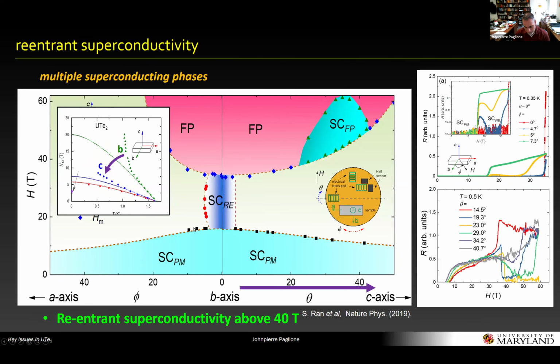Okay, so this well-known phase diagram from Sheng's work early on at Tallahassee also discovered this high field reentrant phase up in the pulsed field regime. It's just slightly observable in Tallahassee fields of 45 Tesla, but you really have to go to higher fields to see it properly. And this has been since refined.